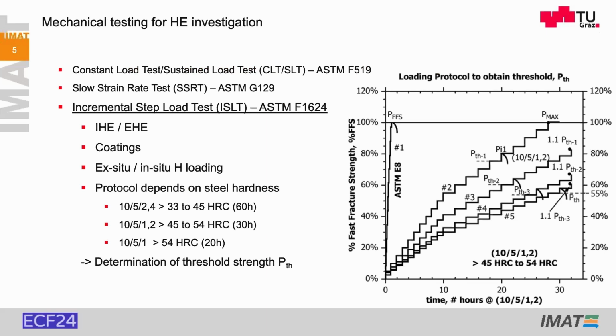Yeah, we chose the ASTM incremental step load test to reach our goals. Probably you know it. It works via the so-called threshold. You make a stepwise loading, and as soon as you get invariant to the loading rate, you get the threshold value which you can use for design or to optimize your heat treatment. And this protocol according to ASTM depends just on the hardness of the steel.